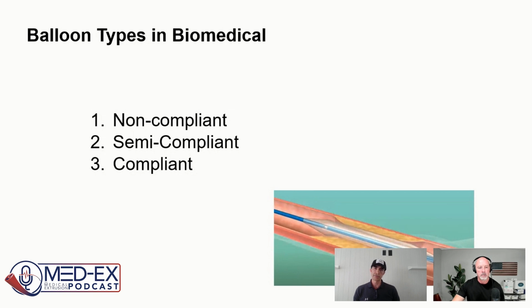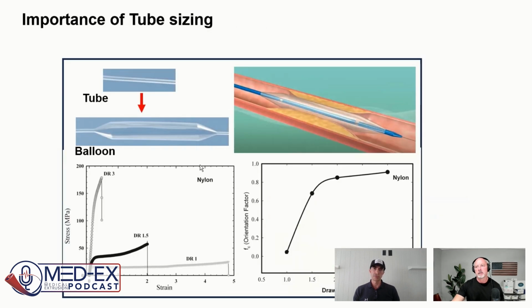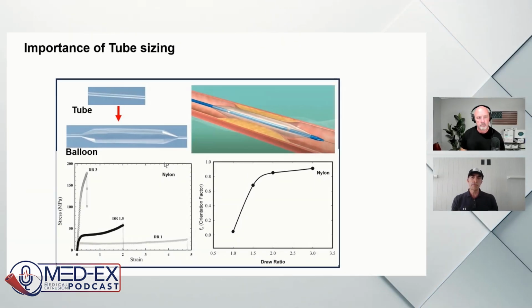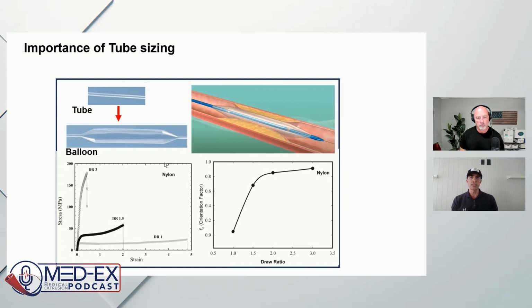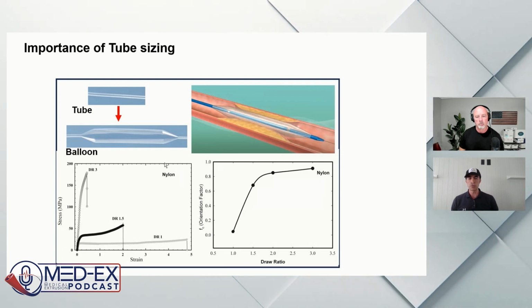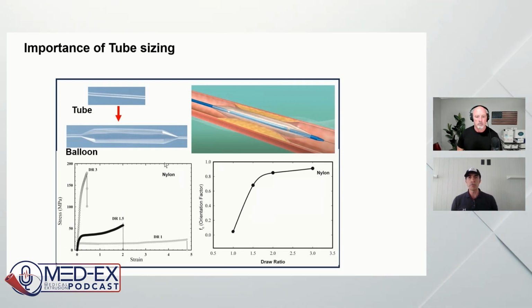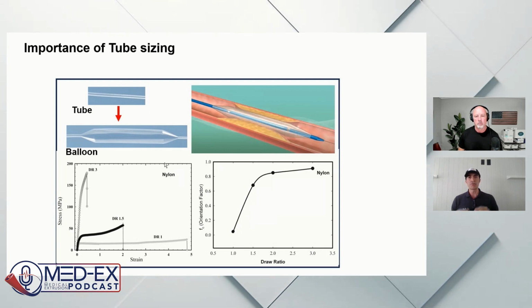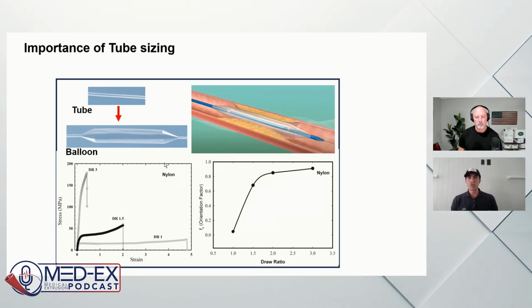Okay. Thanks for that starter there. Now let's talk a little bit about the importance of balloon tubing extrusion in the process. Yeah, I would say probably the most important aspect of the balloon development process is the extrusion tube. And you know that a tube is a precursor to the balloon. So we extrude the tube and we stretch it, or blow mold it, in a process where the tube is stretched in the axial and radial directions. And the tubes are usually sized based on an expansion ratio above 3, so between 3 to 6.